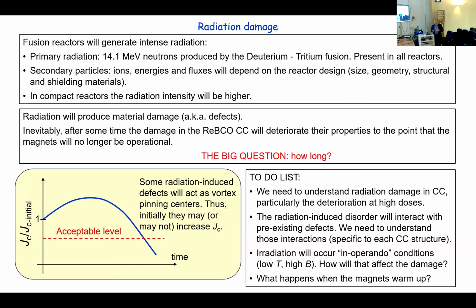So the to-do list for the community is to understand radiation damage in coated conductors, particularly the deterioration at high doses. We need to understand that this disorder will interact with pre-existing defects. And then the outcome will be different depending on what those pre-existing defects are. The other thing that is not very well explored is that this irradiation will occur in what they call in operando. It will be at 20 Kelvin and in the presence of a high magnetic field. I don't know if the field will be that important, but certainly the 20 Kelvin will be important. It will be different than irradiation at room temperature because of annealing effects.